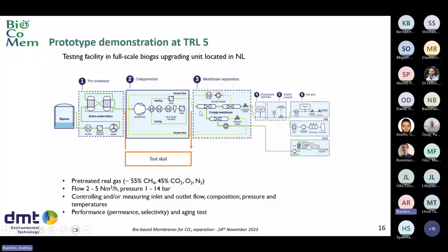it's a full-scale biogas operating unit. There is the digester, then there is the pretreatment, the compression system, and then the membrane separation. So what they did, before the tube that is going into the membrane separation, they spill a part of the biogas, of the real biogas. They send it to a test skid, and then they recirculate it inside the same full-scale unit. So what they get is a pretreated real gas with the composition of 55% of methane and 45% CO2, and then minor components. For a flow rate that can range from 2 to 5 normal cubic meters per hour, and the pressure that can range from 1 to 14 bar.